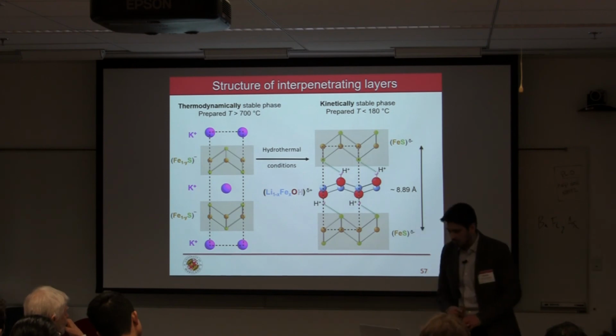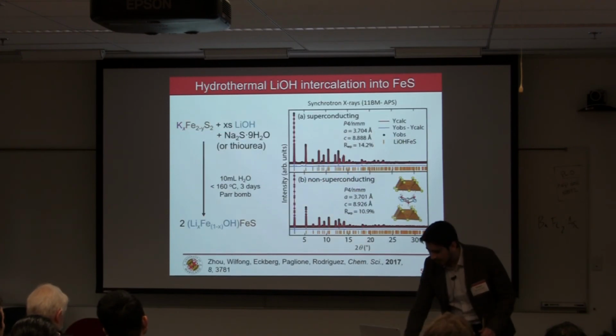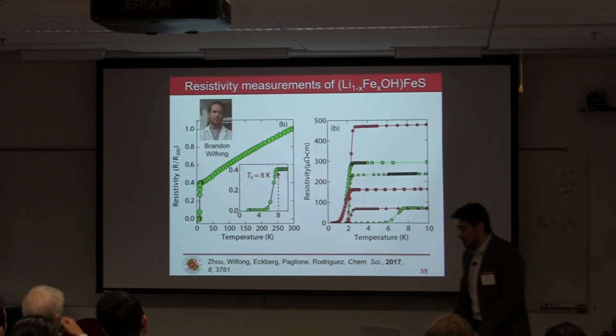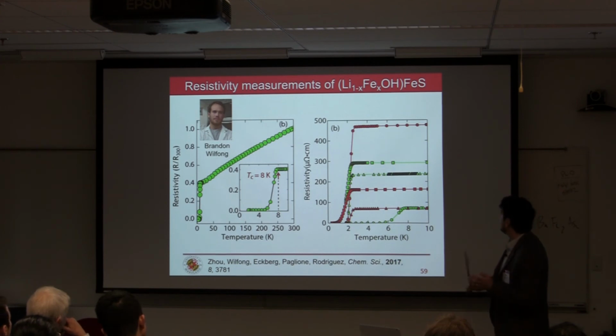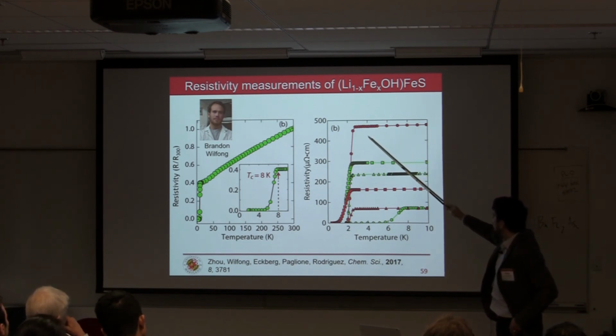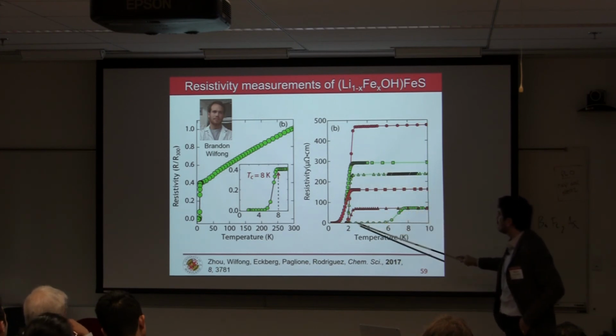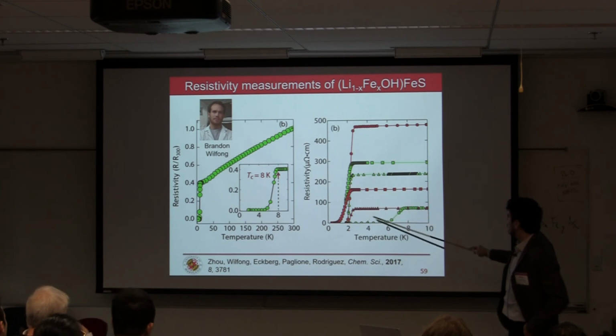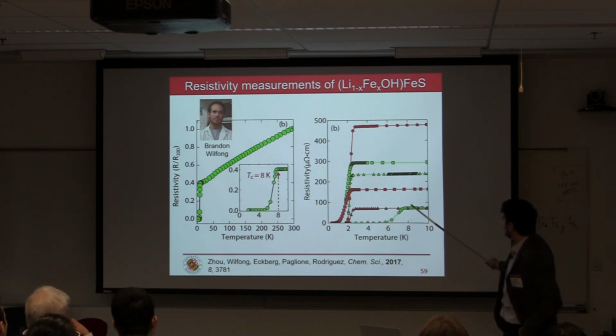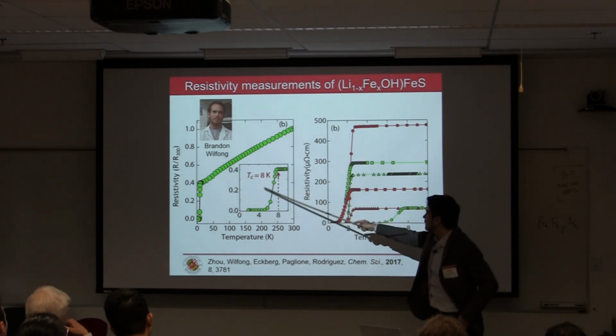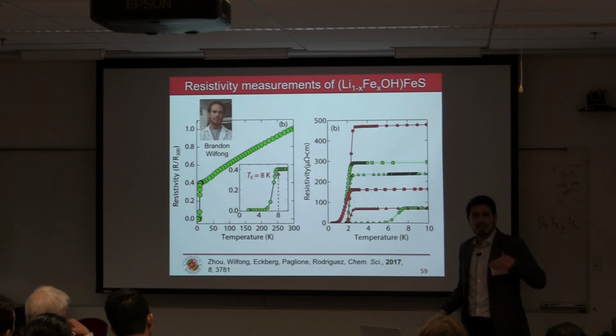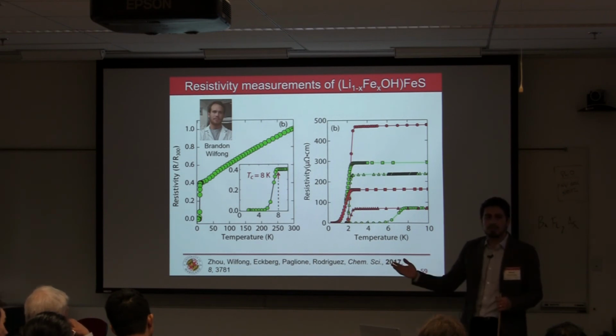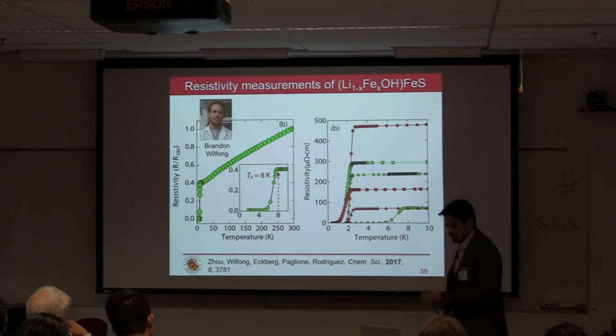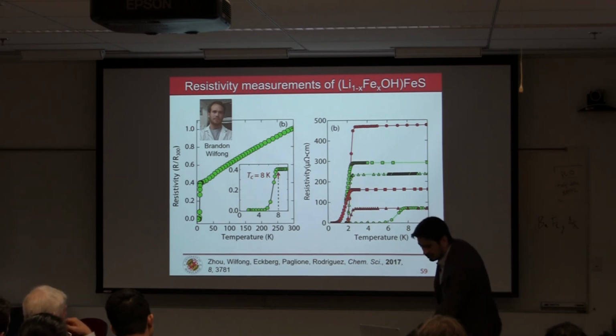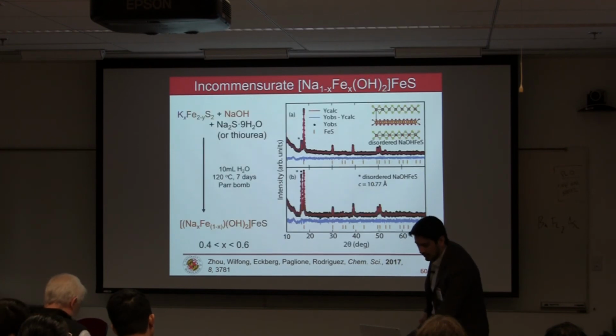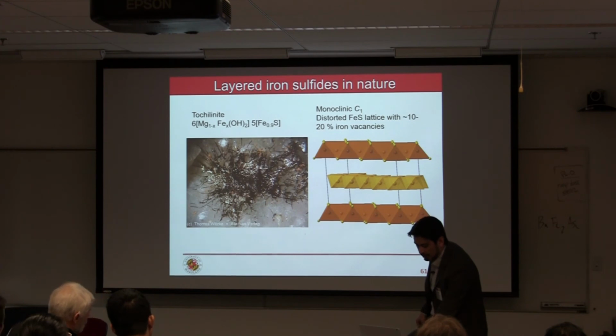Because I don't want to keep you from your coffee break, I'll just show you that we are able to make some new superconductors this way. These are the lithium hydroxide iron sulfide superconductors. With a lot of the samples we weren't able to get above the Tc that you could see in a simple iron sulfide, but in some cases we were able to pick up the temperature to 8 Kelvin. But you can see this is very different from the iron selenide, where upon intercalation they're able to raise it from 8 Kelvin to 42 Kelvin. Here the most that we could do is about 8 Kelvin from about 3.5. So sulfide seemed very interesting to make, but it turns out that it's harder to make higher temperature superconductors from it.